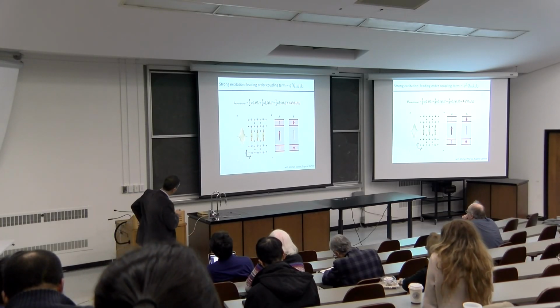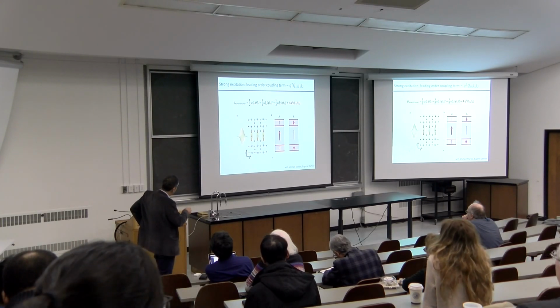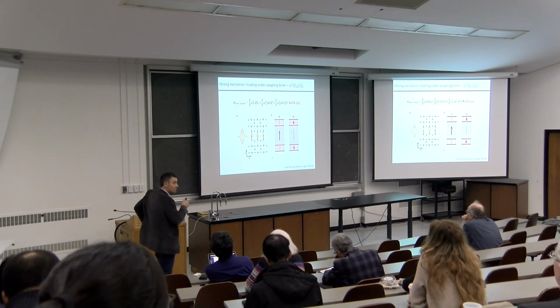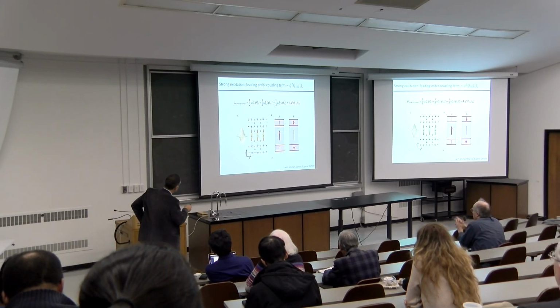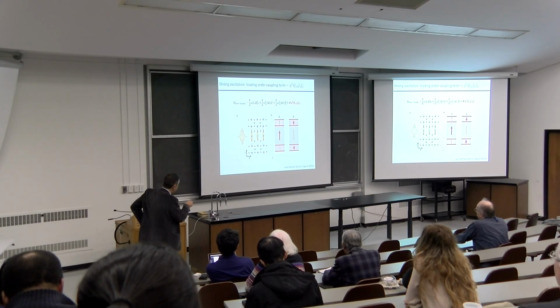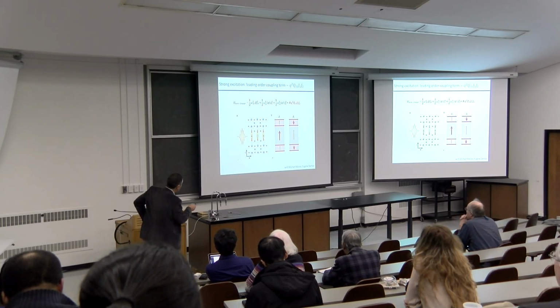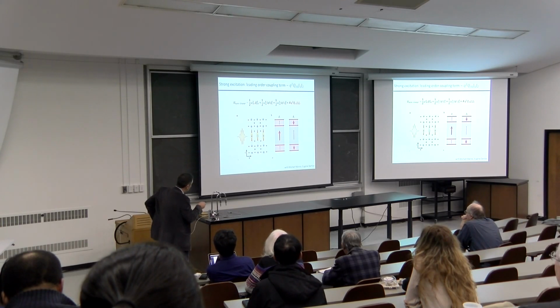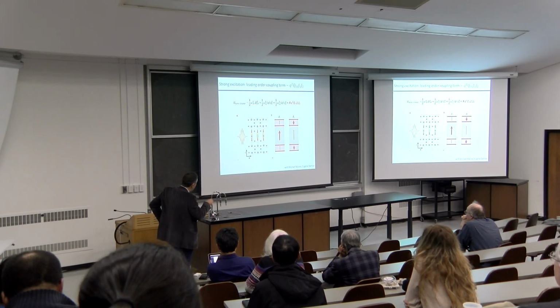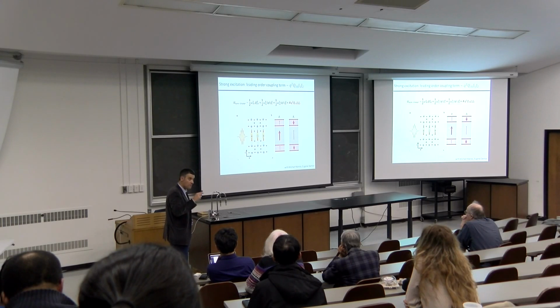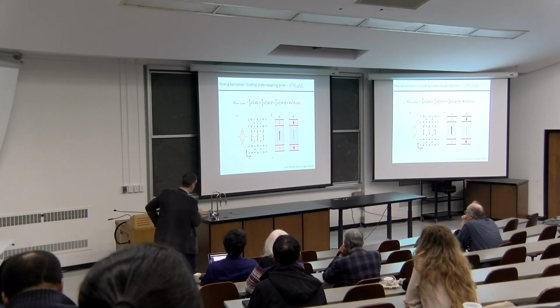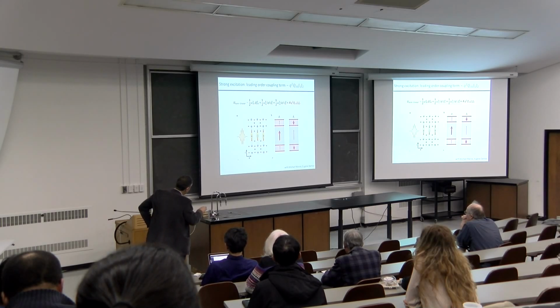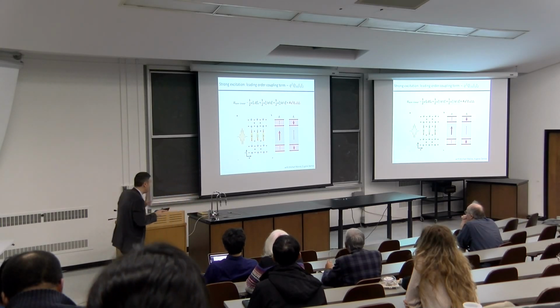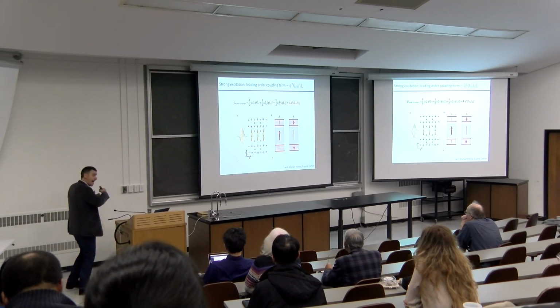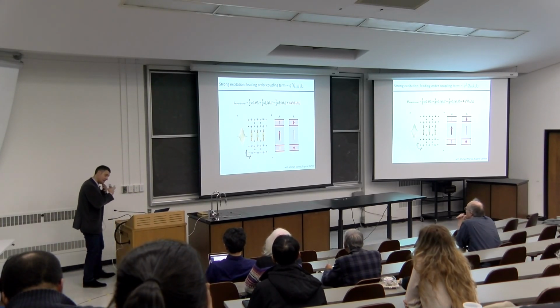And what they told us is that, look, if you take this apical oxygen mode and you drive it to large enough amplitudes, these are the contributions to the energy, the linear energy of the three normal modes. The lowest order coupling is going to be one which is proportional to the amplitude of this odd phonon, and then the product of this specific tunneling and that specific tunneling. I could walk you through the math, but I would put you to sleep and lose 3/4 of the audience. So you're just going to have to believe me. Whereas Q, this is a momentum in the planes. Okay? So there's higher order terms, but this appears to be the strongest coupling term.